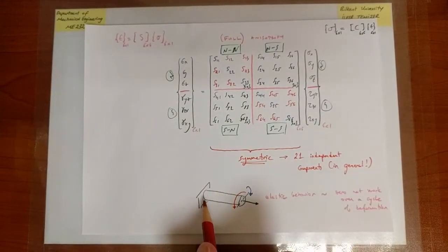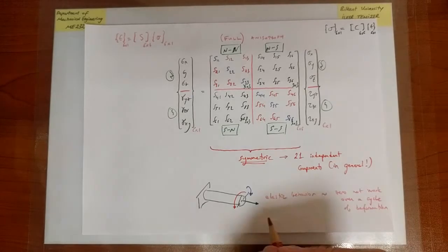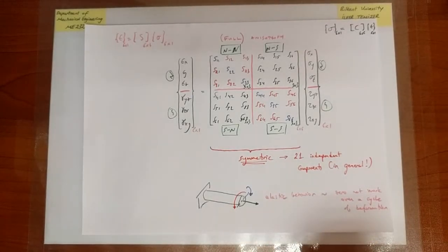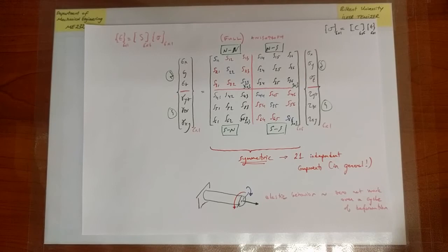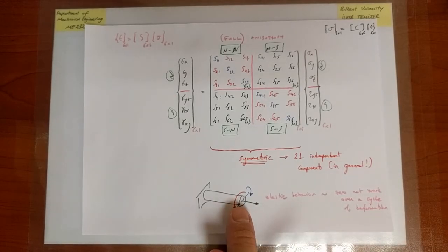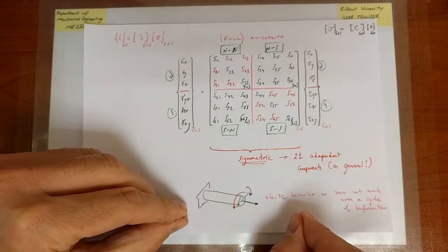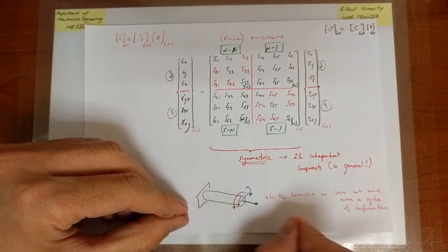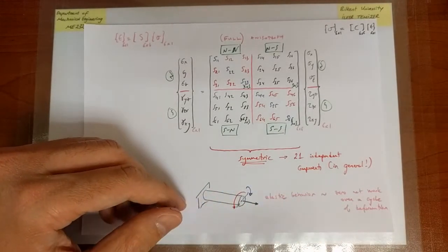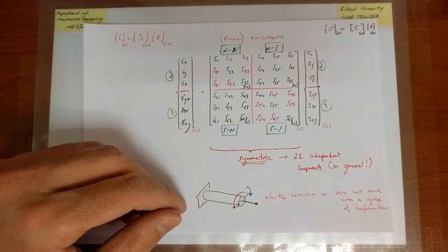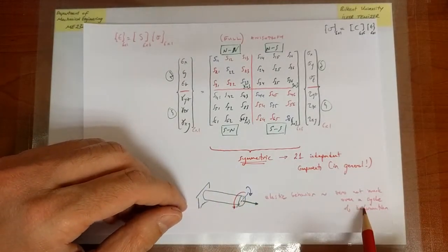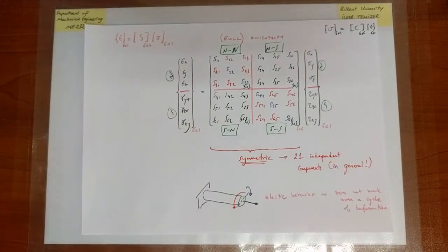Well, because if I deform something plastically, I know that after I remove the load, there's a certain amount of deformation remaining. And in fact, I know from experience that deforming something plastically can require a lot of work. I feel that I put work into breaking something, into deforming something permanently. Whereas that's not the case with elastic deformation. You take a spring, you extend it easily, gives back all its strain when you remove that load. So you don't feel as though you're doing as much work, and in a theoretical setting, the work you do, of course, would be exactly equal to zero.